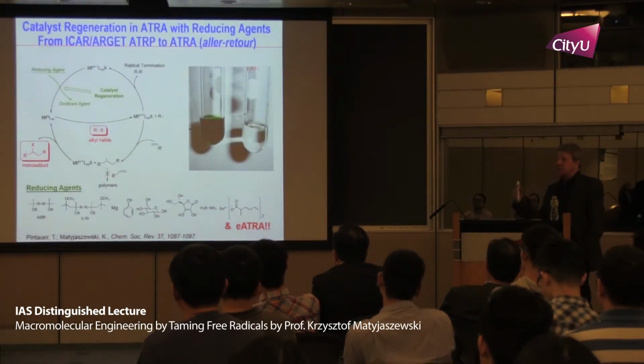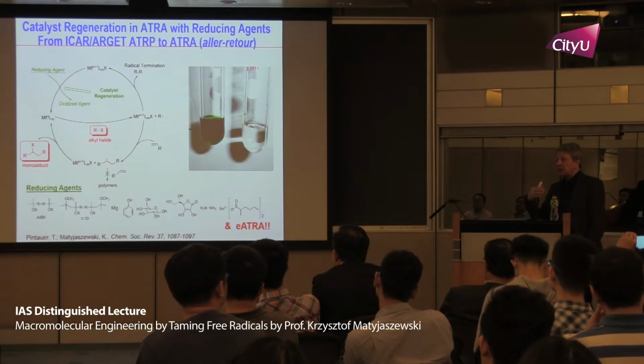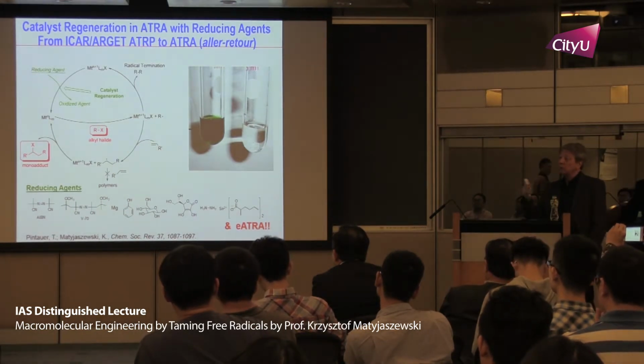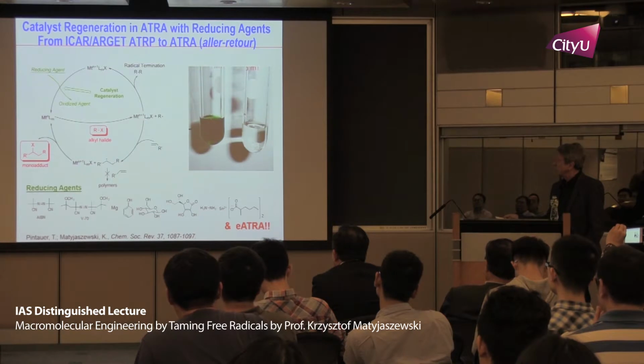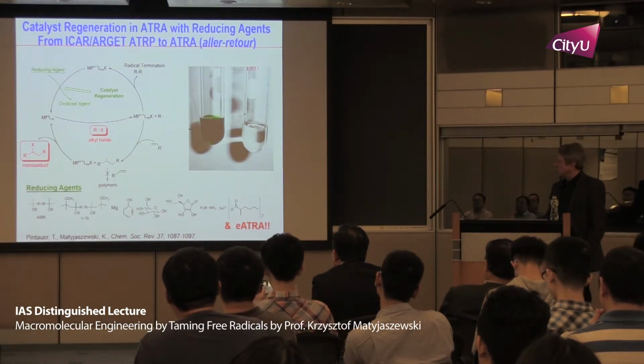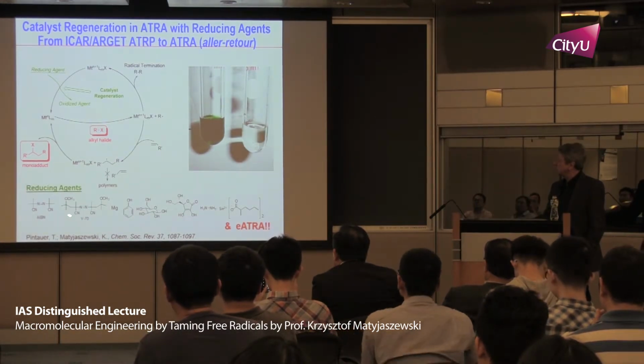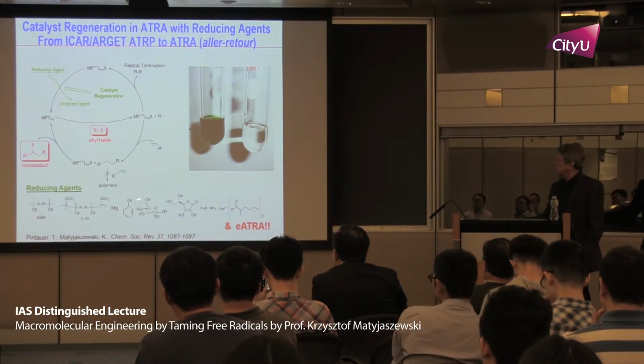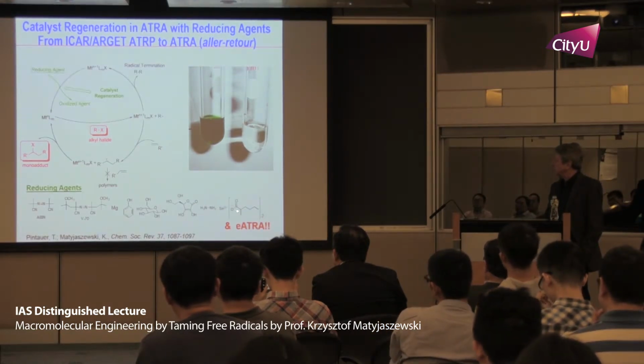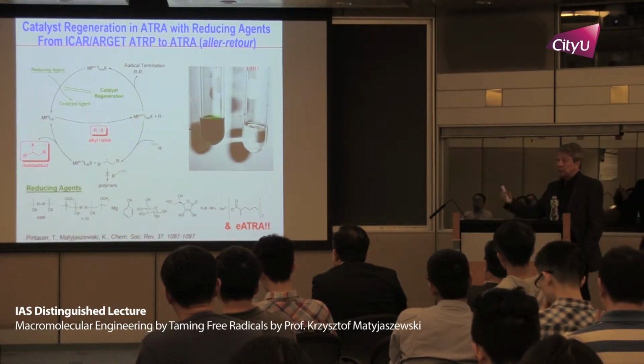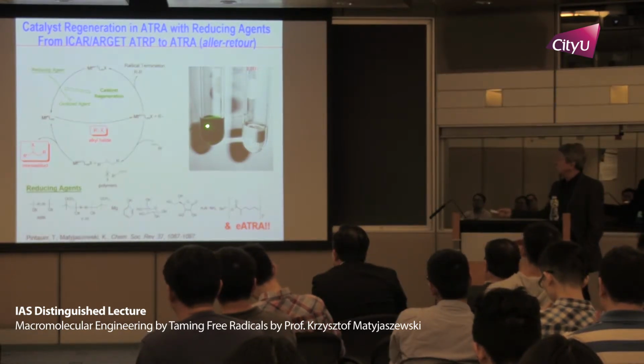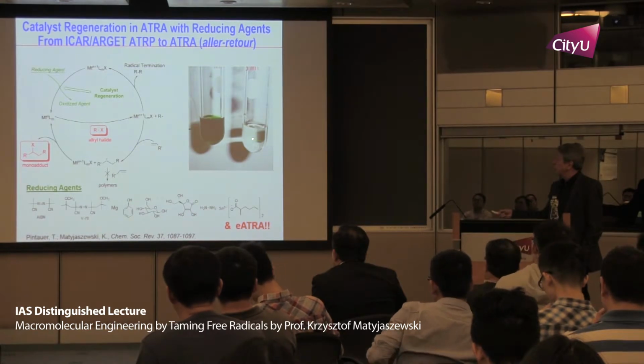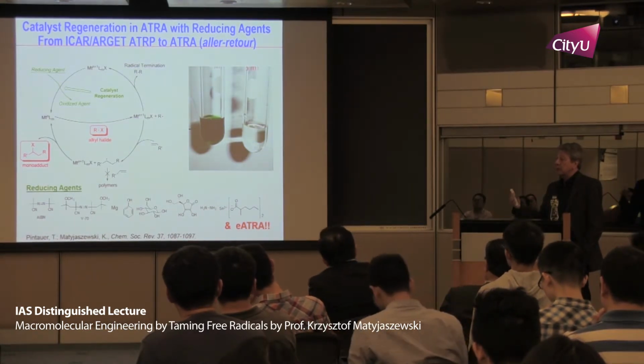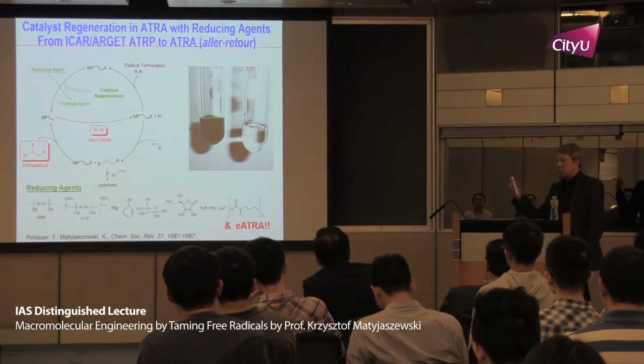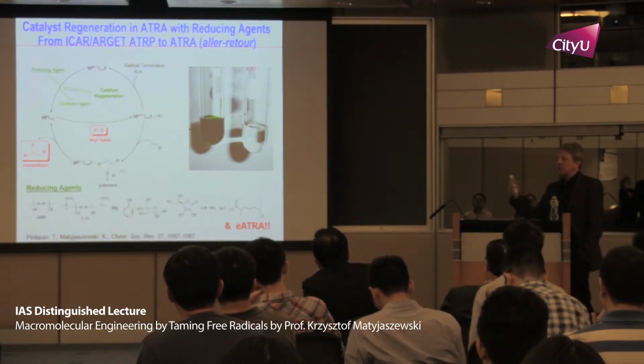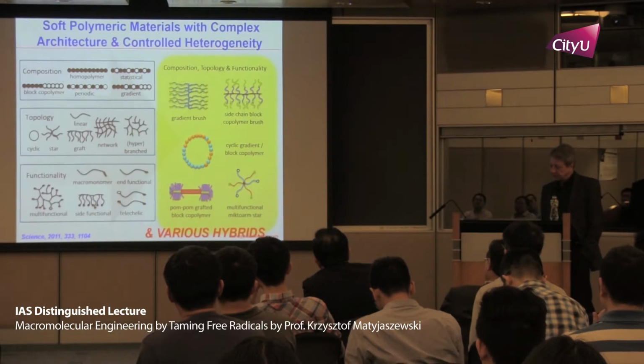So with these catalysts, organic chemists can now borrow our ligands, like we originally borrowed from them these BPY systems. You can use various reducing agents, including radical initiators, sugars and ascorbic acid, tin compounds, electrochemical approaches, and light approaches. Instead of using 10 mol%, you can use 10 parts per million, a completely clean, clear reaction. So it would be important for organic synthesis, making pharmaceutical compounds, and so on.